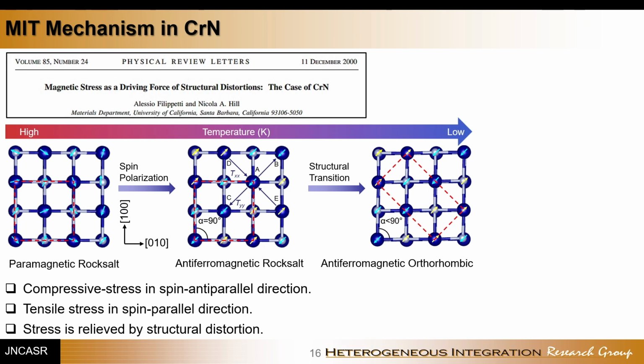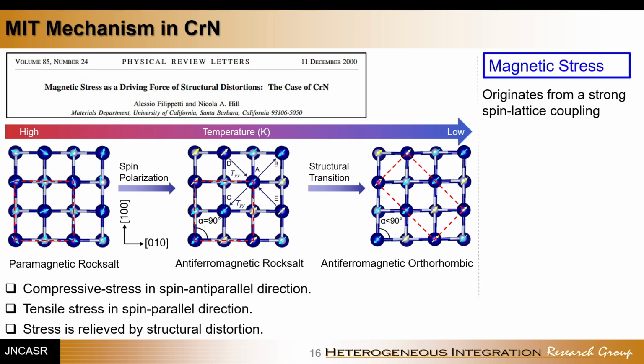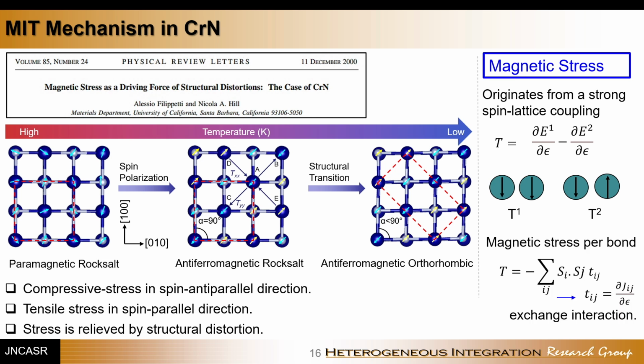And once you create a structure like this, you realize that neighboring spins which are pointing in the same direction will repel each other, and the opposite spins which are close to each other will try to come together, and as a result you will see a structural distortion. So the material undergoes an antiferromagnetic rock salt to antiferromagnetic orthorhombic structural transition. And this, she explained with the help of magnetic stress in a material, and this magnetic stress is basically the first derivative of the exchange energy. So for a long time, this remained as a theory because people were not even sure how to make chromium nitride which reproducibly shows metal insulator transition.